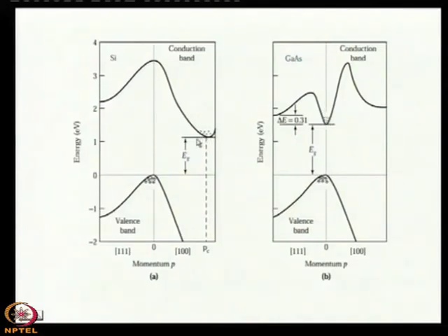Right. So, this picture shows you two types of bands. Let us come here. There are two types of band. One is you see that the bottom of the conduction band or conduction band minimum, and it is the valence band maximum, and they are not on the same K value or momentum value, because on the x axis the P is plotted, momentum is plotted.